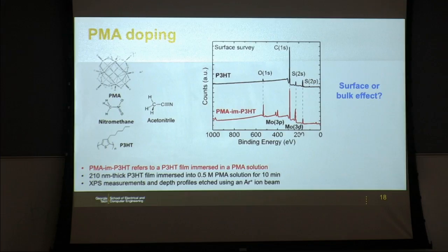And so just to show you that this is what's happening, these are XPS data, and these are just measurements of the surface of a film of poly-3-hexyl-thiophene. This is a well-known semiconductor that's widely used in organic solar cells, for instance. And you see on top here is that phosphomolybdic acid diluted in the various solvents. And the solvent is very important here. It works either with nitromethane or acetonitrile. And you see this is what's called a Keggin structure. It has 12 molybdenum atoms. It has a phosphine oxide core here, and has oxygens surrounding this molybdenum. It's a well-known reagent in chemistry, but as you will see, it works really well as an electrical dopant, as a p-type electrical dopant.